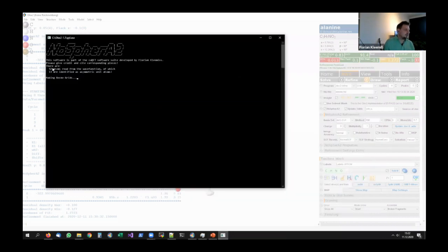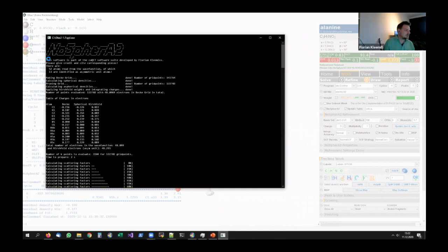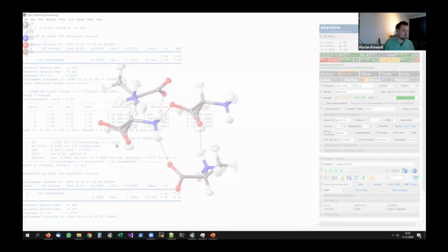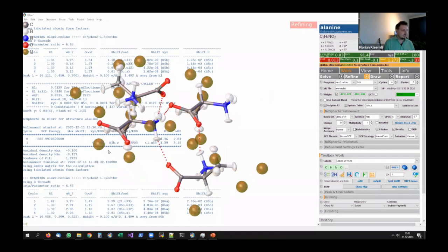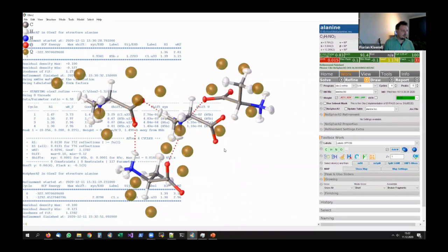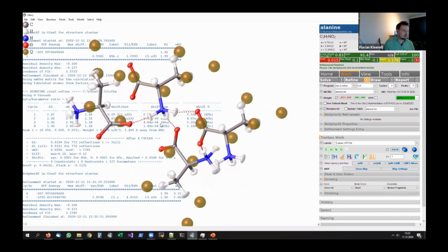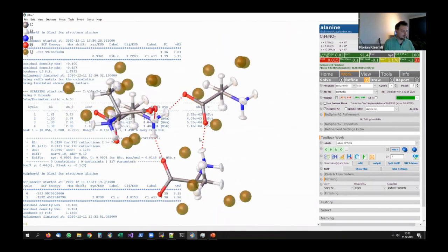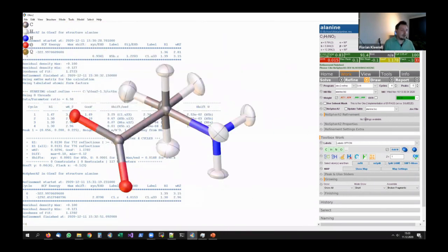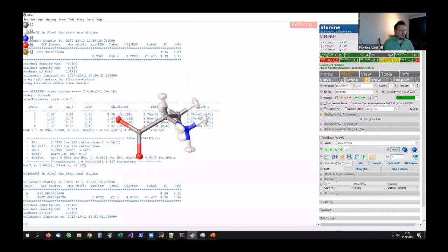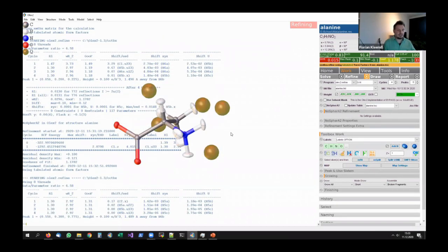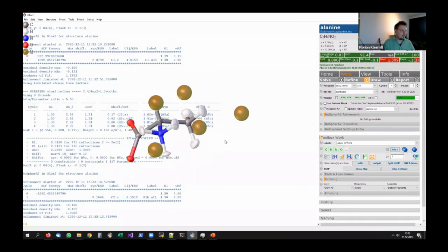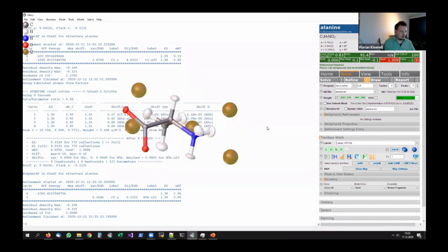So now you can see we have 52 atoms in the wave function, but only 13 of them are the asymmetric unit and were included in the calculation of form factors. And now you can see this amine function behaves much more nicely compared to the previous calculation. Now that I have the table, I do not need the cluster anymore. Now I can refine without the neighbors being present. I can do it again, but this is now done and I can work with it.